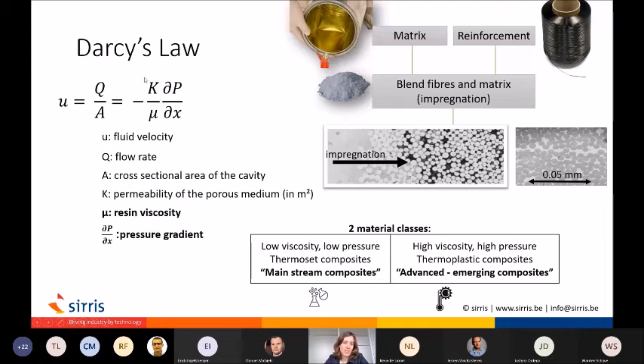The first one is the permeability of the porous medium, or of our fiber bundle in our case. We can assume this is more or less constant, so I will not talk about this a lot. What is important is the pressure gradient. It's quite easy to understand. The more pressure you put on the resin, the more easily you will impregnate your fiber bundle.